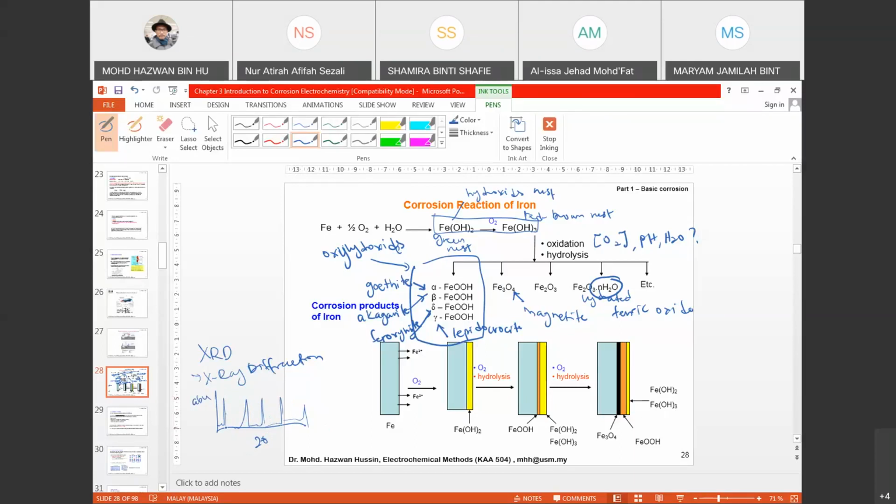Maybe over here, around 10 degrees, 30 degrees, this is related to what? To goethite, for example. Then you know, okay, G, and then this one may be M, and then L. This is how we indicate it. Most XRD machines are equipped with a library, meaning they already have a standard for goethite. So for goethite, the 2 theta will appear at specific values, akaganeite at specific values, magnetite and lepidocrocite.